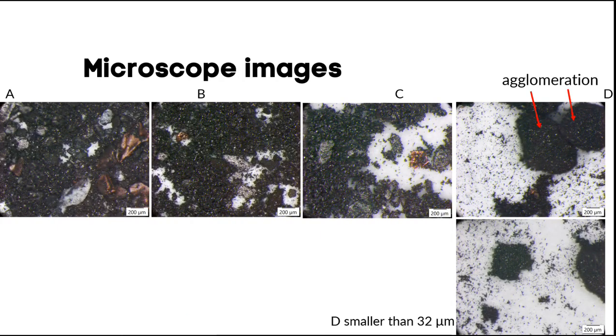And before we do the experiments, we first took some microscope images. We see some brown and silver larger particles in the samples, and probably they are the current collector, copper or aluminum foils remained in the black mass. In one of the samples, we can see obvious agglomeration, where smaller particles come together and form bigger particles. With one of the materials, we sieved to take away the bigger particles, and we didn't see those brown and silver particles there.